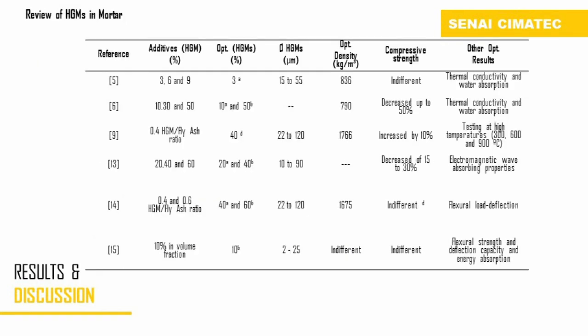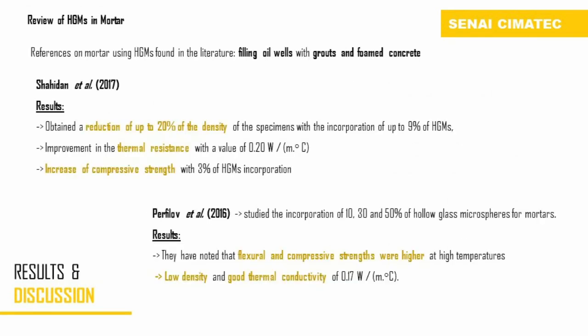Now, the review about mortar. We can see the range of percentage of additives in mortar, also the variability of density obtained and a variable behavior of mechanical strength. In the mortar research, the applications found are fillings, oil wells, and foaming grouts. It is important to highlight the interaction of the amount of HGM incorporated with the reduction of mortar density. Shahidan et al. obtained a reduction of up to 20% in density, with gain of thermal resistance and increase of compressive strength, with 3% of HGM incorporation. The optimal percentage to gain a lower density is 9% of HGM in this result.